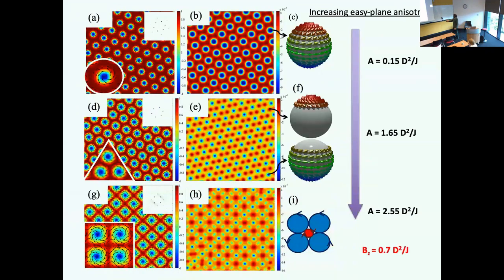And what happens? So on the left column, I have the spin structure. And the blue and red means the Z component of spin. In plane spin texture, can you see from the back any spin texture? And this is the corresponding topological charge density of what is happening. And I'm going to increase systematically anisotropy in that Hamiltonian. So here you see a triangular lattice of skyrmions, and each skyrmion covers a unit sphere once. It is winding number 1. As I go down, these skyrmions start pushing each other, and you start creating some vortices between 3 spins, okay? And then it undergoes the first order phase transition, and you get square lattice of skyrmions, and in between there's a vortex here. This vortex will soon become a meron.